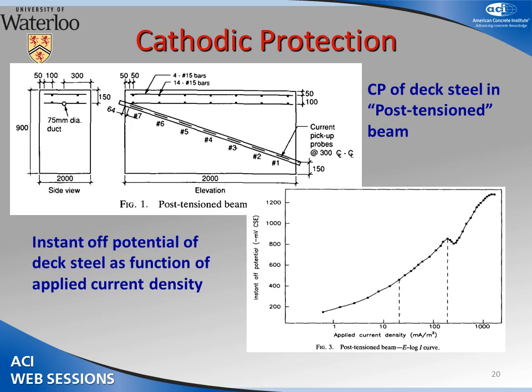However, all the advice you can give is for naught if people don't follow it. At this time, he was advising or working with the Ministry of Transportation to design cathodic protection systems. And there was one system he was working on of a bridge over a railway in Kingston, Ontario. And he specified, never let the potential get more negative than 1 volt on the copper sulfate scale. So he went back a few years later to inspect this and check that everything was going fine, and found the potential was minus 2 volts.